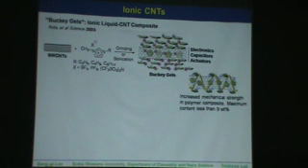But the problem is to increase the mechanical strength, they put in a polymer component. But the limitation is that the maximum content of the liquid is less than 9%. And also, the polyimidazolium ionic polymer and the CNT are not covalently bonded. It segregates. If we mix the components, they are separated in certain cases.